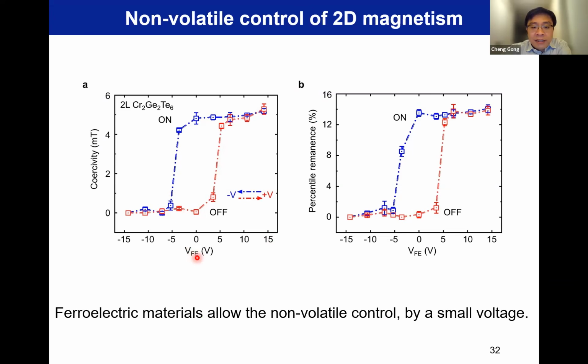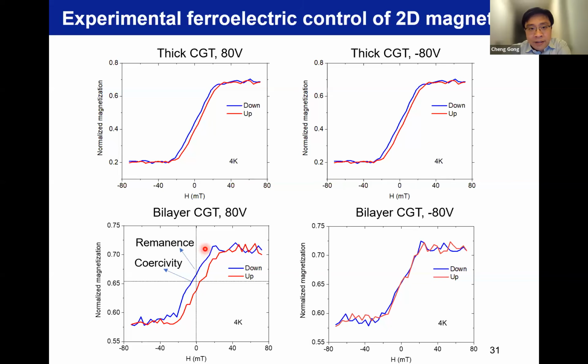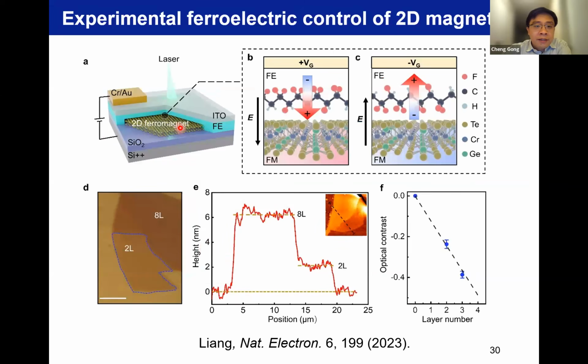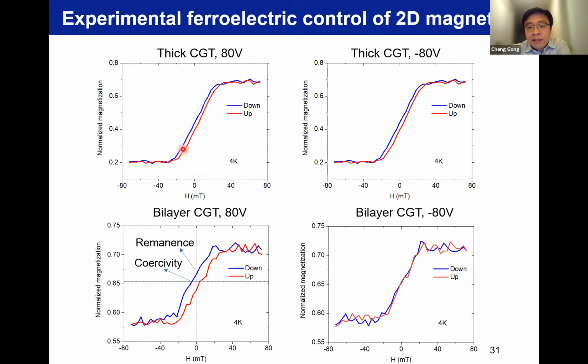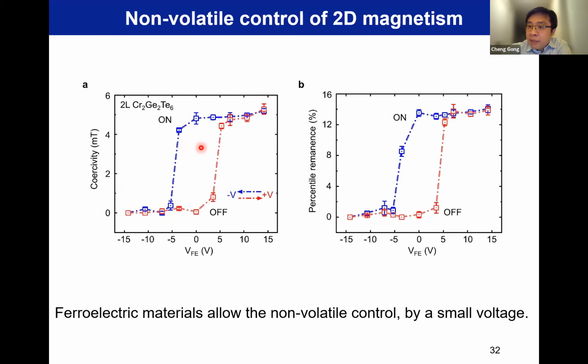Here we summarize the effective voltage only on the ferroelectric layer, because a lot of voltage is actually wasted across the silicon oxide. So you can use a capacitance model to calculate, and the voltage drop on the multiferroic itself is only about 5 volts. 5 volts across 50 nanometers of PVDF-TrFE is equal to around 100 millivolts per nanometer. This is a normal switching coercive field for PVDF-TrFE.